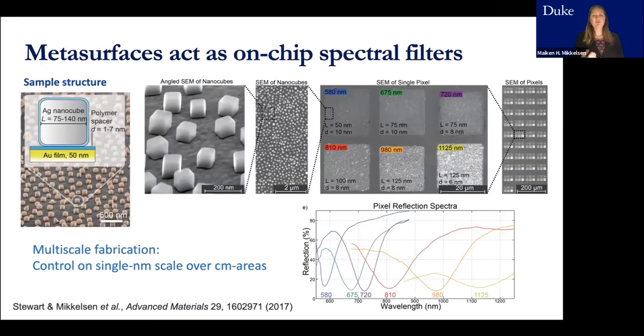And we want to see if we can make it spectrally selective, utilizing these nanocube structures. We utilized them in the past for just picking a plasmon resonance that overlaps well with the emission characteristics of our system. But we can also make these structures without putting any emitters in, and demonstrate how we can make pixels of different spectral bands. As you can see, we make small pixels. In this case, each pixel is an array of 6 little squares, and if you zoom in, each of these squares consists of nanocubes of a particular size. The size of the cubes and the gap thickness are what we can change to tune the plasmon resonance.